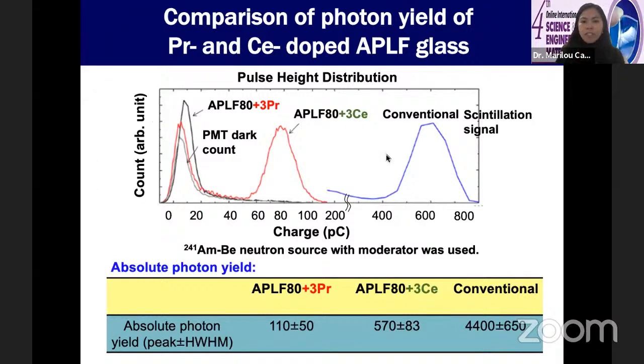So comparing the performance of the scintillators in terms of the light yield, we can see here the conventional scintillator has a very high photon yield, so much higher compared to our APLF scintillators. But focusing on our APLF scintillators, we can see that doping with cerium achieves a higher photon yield compared to doping with praseodymium. So sure, we can get a very fast response time with praseodymium doping, but that sacrifices the photon yield. If we dope with cerium, we get a high light yield, but that also sacrifices the decay time. So the decay time is longer for cerium.